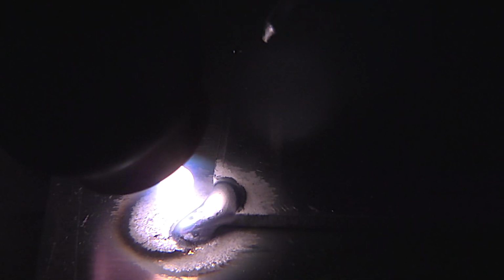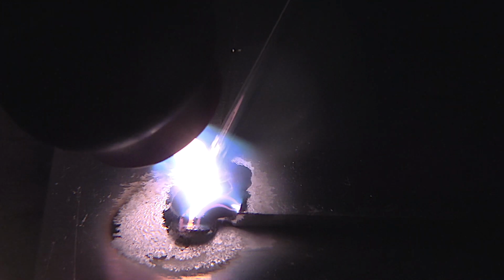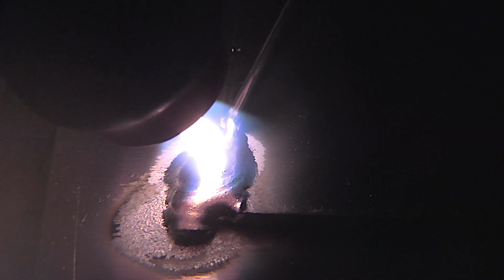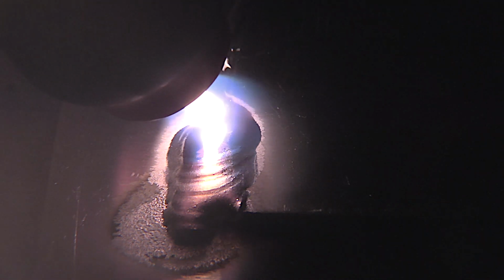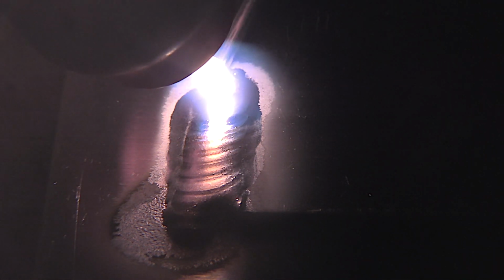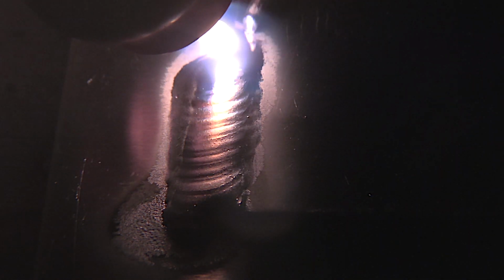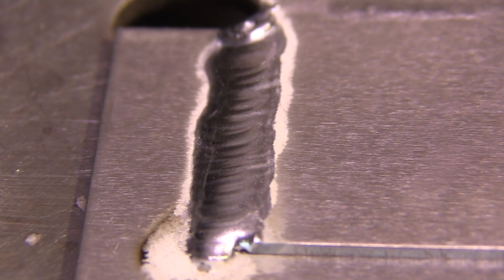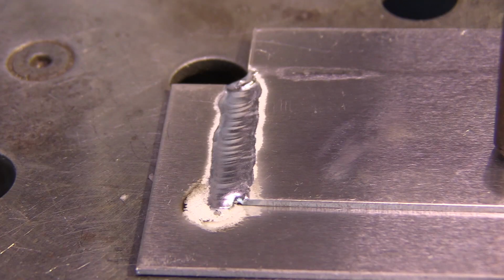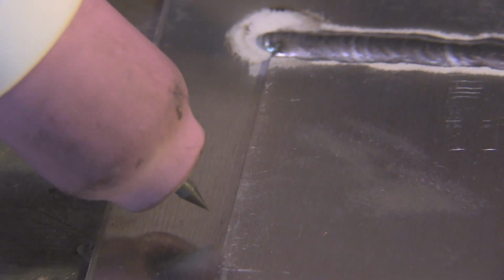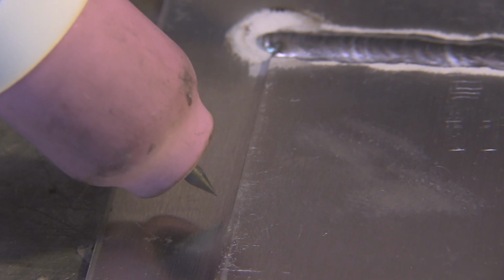I've also got a little porosity showing up in the tack here, as you can see, probably because I didn't clean the metal enough. All I did was a quick acetone wipe, and it had a little layer of oxidation. But you can see, this is doable. I mean, you can make a bead on it. It's a lot wider than it should be and a lot harder to control, but you can weld a lap joint like this with a 3/32 rounded tip. You could also do a lot better dropping down an electrode size with a rounded tip. I just don't like to swap electrodes out that often.